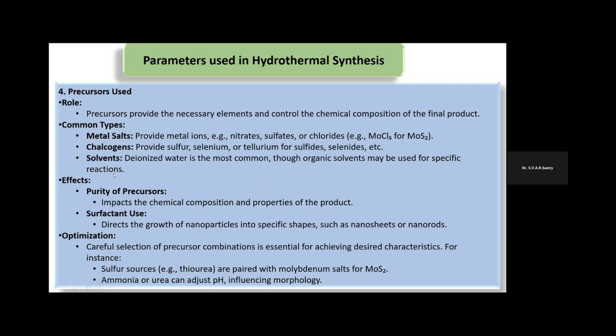Then the effects of the precursors. The purity of precursors is very, very important. It impacts the chemical composition and properties of the finished product, the nanoparticles. Then we can also use surfactants. A surfactant can direct the growth of nanoparticles into specific shapes, such as nanosheets or nanorods.